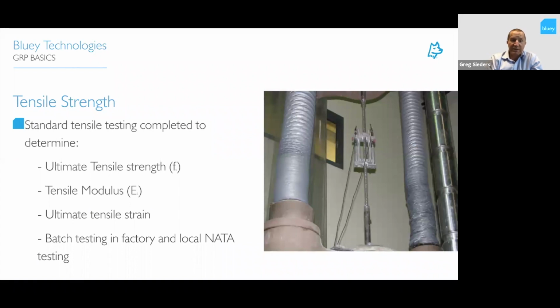Tensile strength. This is standard testing that gets done at time of manufacture. It also gets done as local testing when we import the bars. So it's testing the tensile strength, the modulus, and the tensile strain. Like we talked about, just like a steel product, we get batch testing done on every single batch that is produced to make sure that we're getting the same capacity or the minimum standards. And then when the product arrives in the country, we get local NATA testing as well to back up the testing for the local authorities.